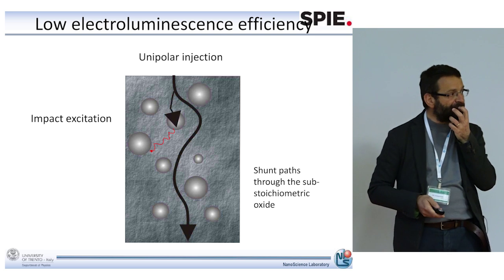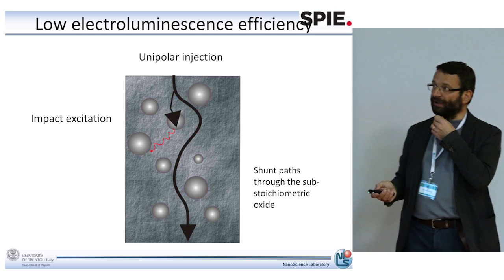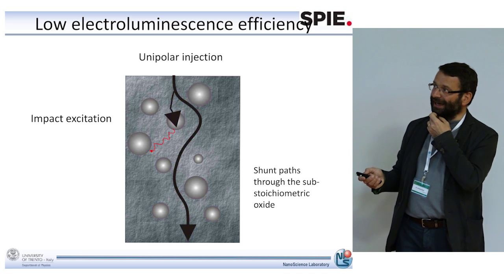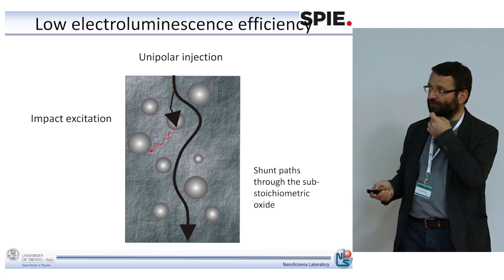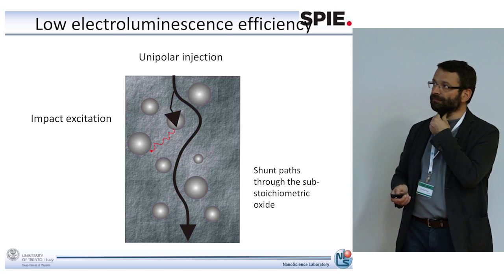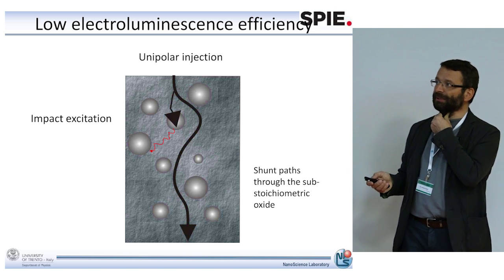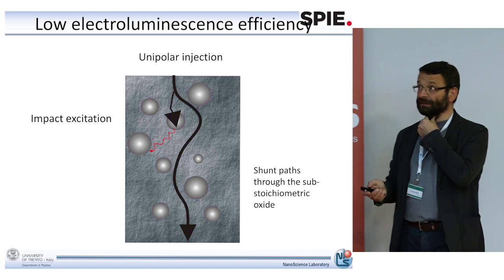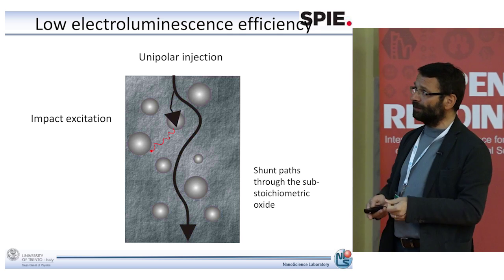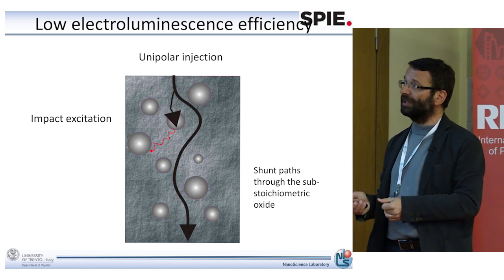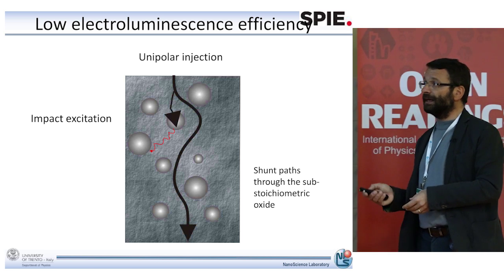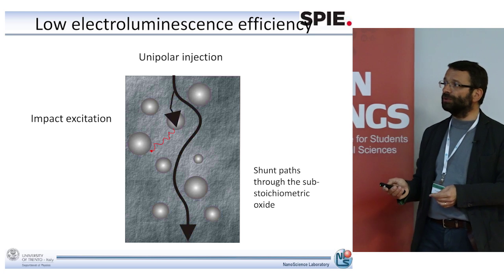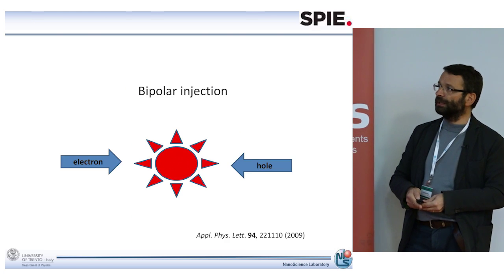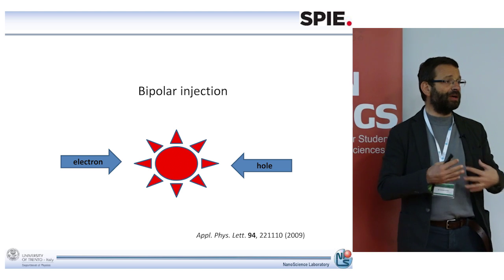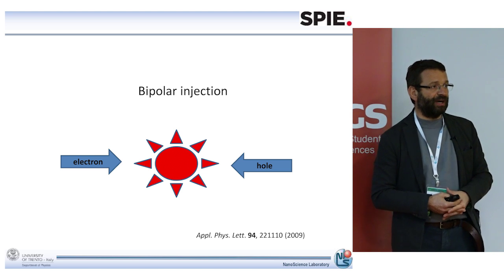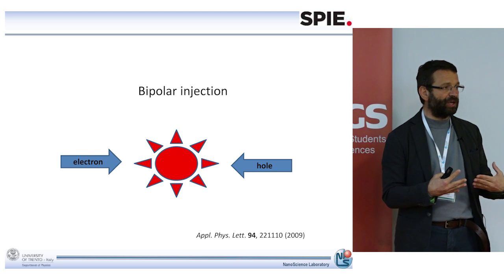The problem with unipolar excitation is that most of the current is going through shunt paths that form in the substoichiometric oxide, and only a few of the carriers have a probability to impact the nanocrystal. That means that by using this technique, the quantum efficiency, the external efficiency of the LED, will be very small. On the other hand, bipolar injection could provide very strong electroluminescence. So now the issue here is how we can manage the fabrication of the device in order to get bipolar injection.